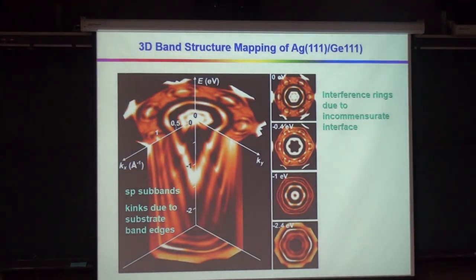Well, I lied a little bit. The things are much more complex. You can actually take a more detailed look by doing this mapping along the x and y directions. Before, I showed just one cut, with one parabola. Now you can see multiple parabolas in one cut. You can also look at the cut along different directions. So basically, you get a paraboloidal surface. Each atomic layer gives you a paraboloidal energy surface.